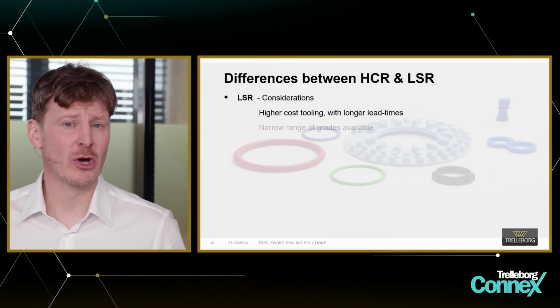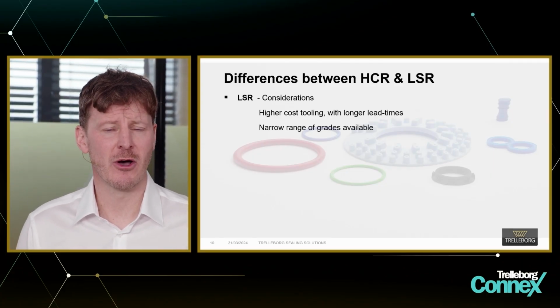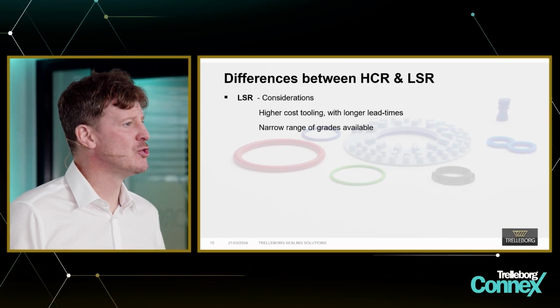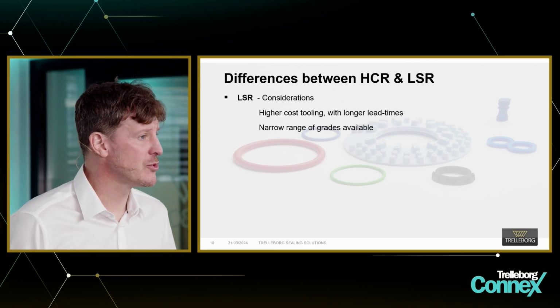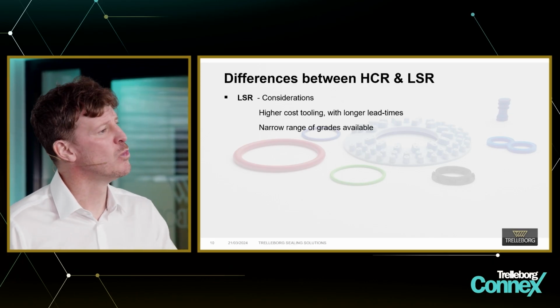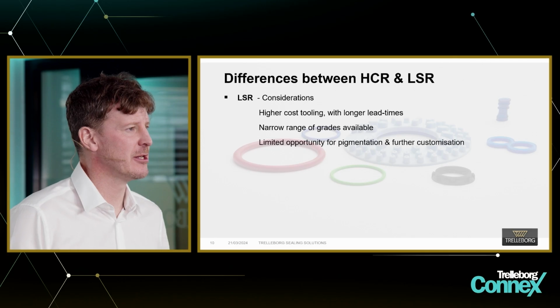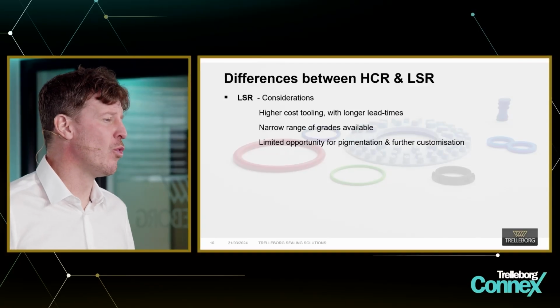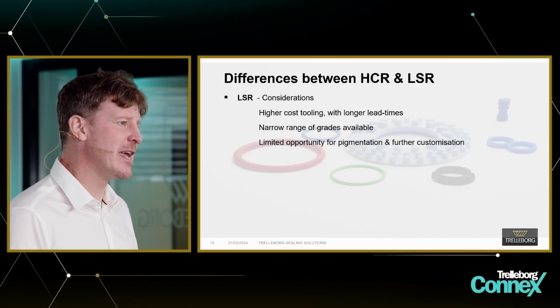Now, there are some considerations with liquid silicone rubber. Generally, the tooling cost is much higher, and the reason for this is that the accuracy of the machining is incredibly important. Surface ground finishes and so on and so forth. This leads to longer lead times, but the tooling cost, as I mentioned, is higher. There are a narrower range of grades available. There are lots, but it is still slightly less than what can be done with high consistency silicone rubber. There is limited, or more limited, opportunity for pigmentation and further customization. And the reason for that is due to the viscosity and the nature of the material.